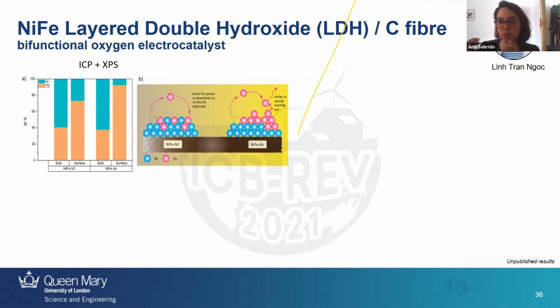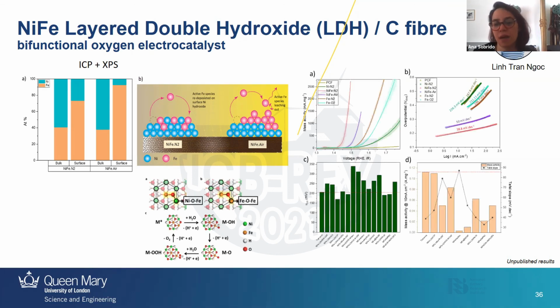One of the things that we're trying to understand is whether it has anything to do with the way that these irons and nickels are coordinated in the structure at the surface, essentially. But what we are finding, in summary, is that they perform really well. Here, the first column is our work, and this is the rest. So our overpotential is not the best, but it's not bad, which is very good. Our kinetics, our Tafel slope, is the best. So we are really pleased with that. We just need the last bits of understanding to really be able to understand the system.